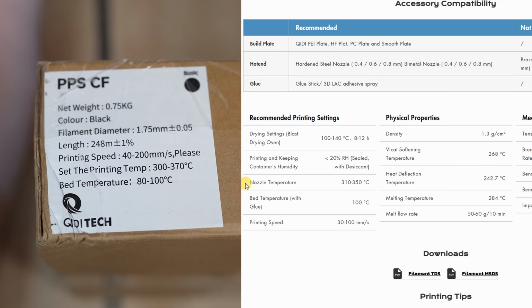Now let's see some print settings, and we have different information on the box and on the website. Here you can see them side by side, but info from the website: the print temperature between 310 and 350 degrees Celsius, bed temperature 100 degrees Celsius, and the speed up to 100 millimeters per second. And they recommend some drying if necessary, between 100 and 140 degrees Celsius, for 8 to 12 hours.